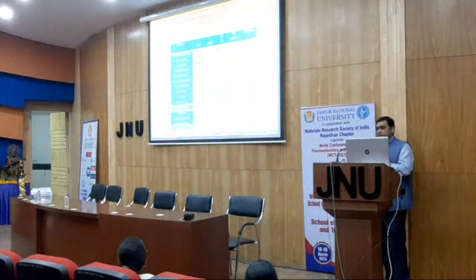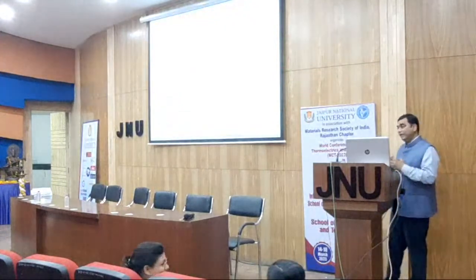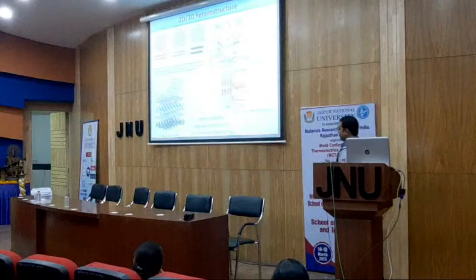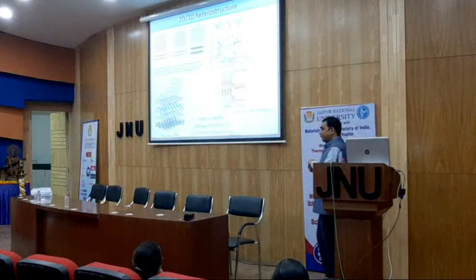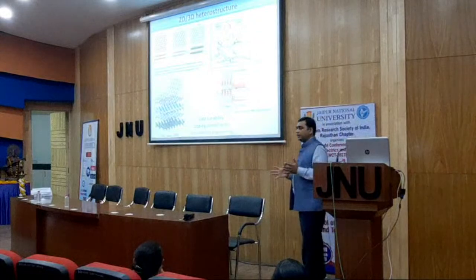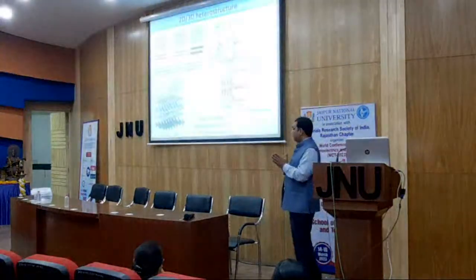So now to address this issue, we have tried to form 2D-3D structures using 2D materials. These are 2D materials like graphene, hexagonal boron nitride or MoS2 or so. These 2D materials have very strong bonding in plane and very weak bonding between the planes. You know, the band gap can also be tuned depending upon the number of layers. The advantage of 2D-3D heterostructure is, the first one is gate tunability. The doping can be controlled easily in 3D and no interface engineering is required in 2D material. So if you are going to develop a 2D-3D heterostructure, these are the advantages.